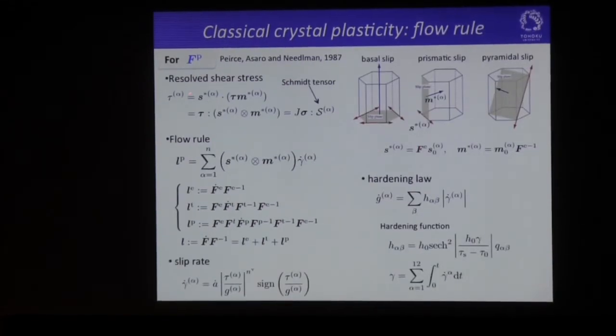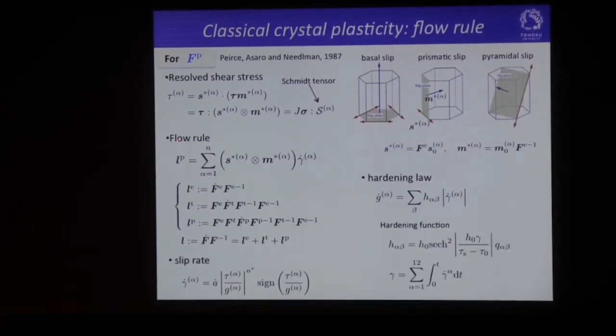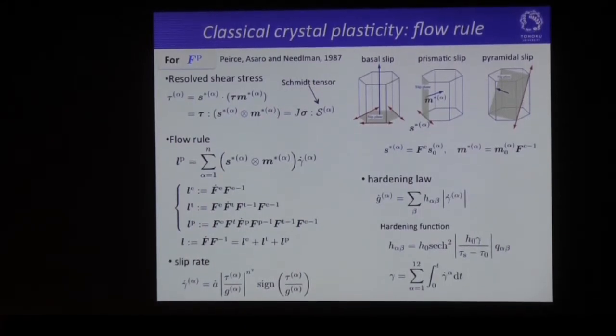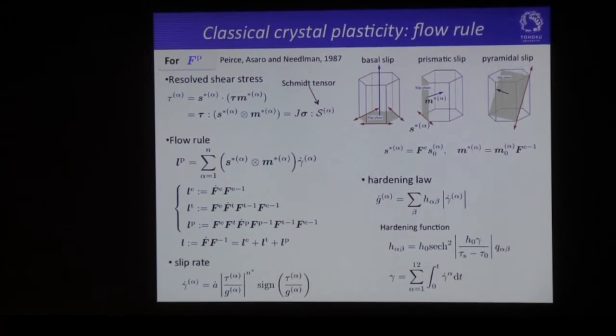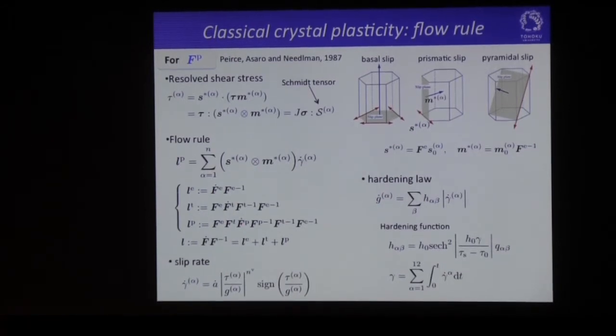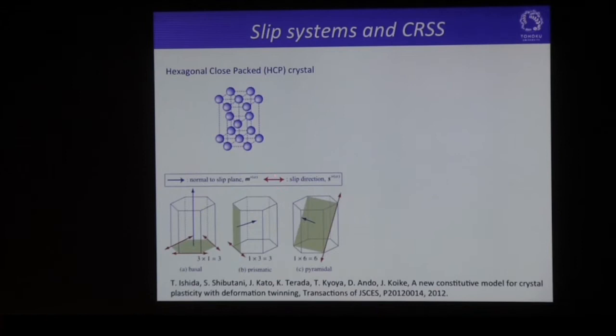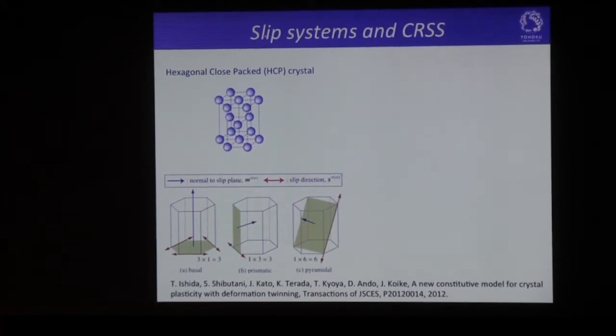But here is the standard expression of the resolved shear stress. Here is the Schmid tensor here. And this is the famous typical expression for the flow rule using the Schmid factor. And also this is the hardening law and the slip rate here. But we have to be careful about the characteristics of the slip system and critical resolved shear stress of this material.